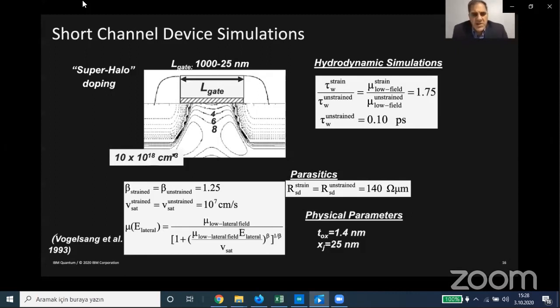Actually, I simulated down to 25 nanometer gate length, and the doping was chosen to have good electrostatic control of the channel down to 25 nanometers. And you can see here the doping levels were very high, as high as 1E19 in the pocket, the halo pocket. So a key question of this study is, if the strain-induced mobility enhancement is reduced in the Coulomb scattering regime, as I showed you before, then for such high doping levels required for nanoscale MOSFETs, will we still see a benefit or not?